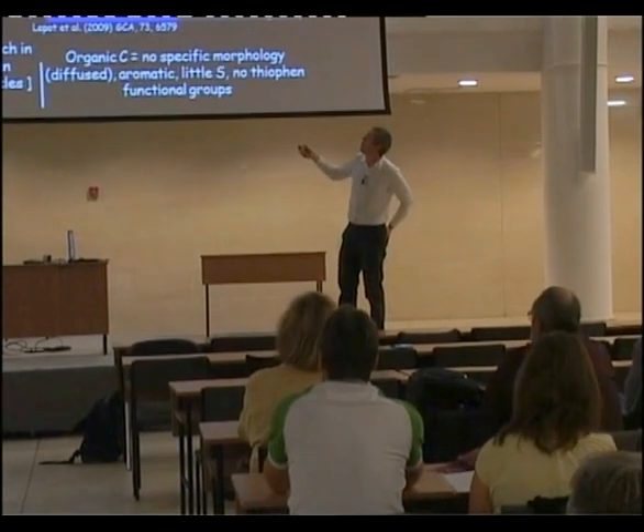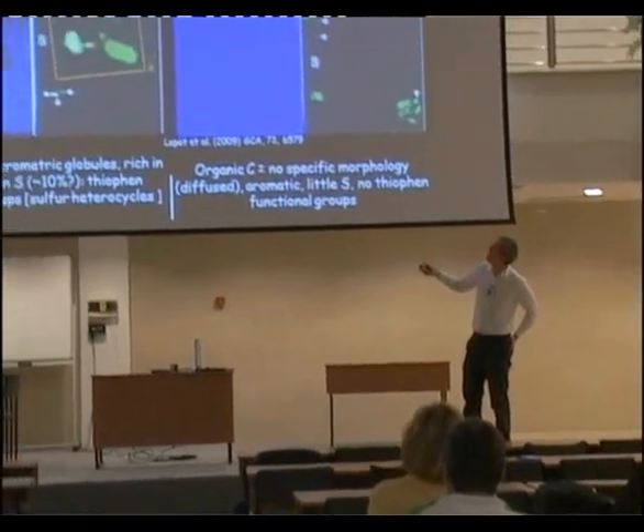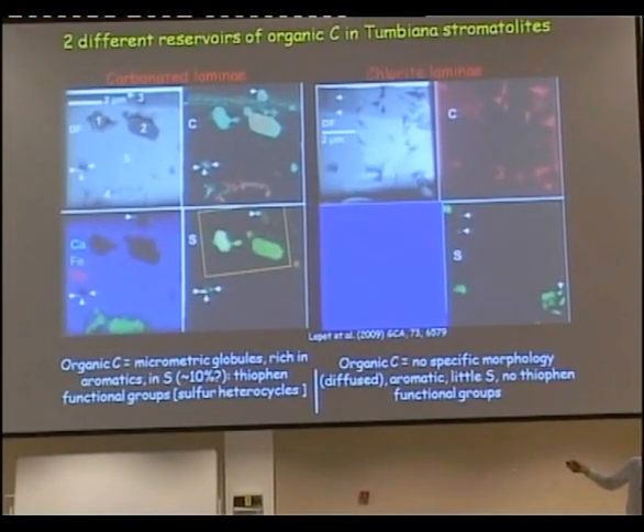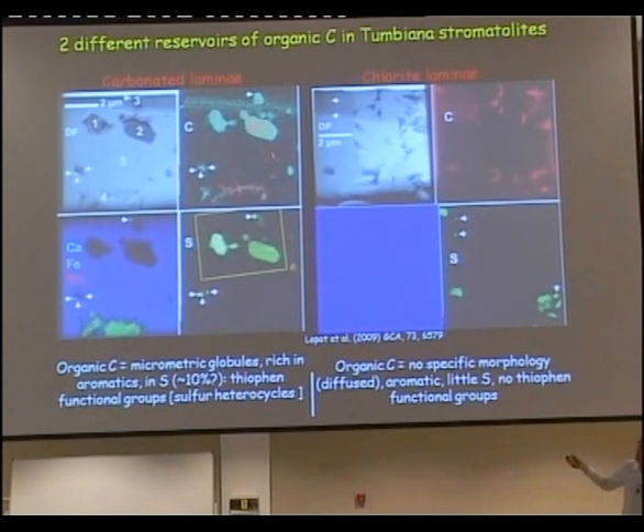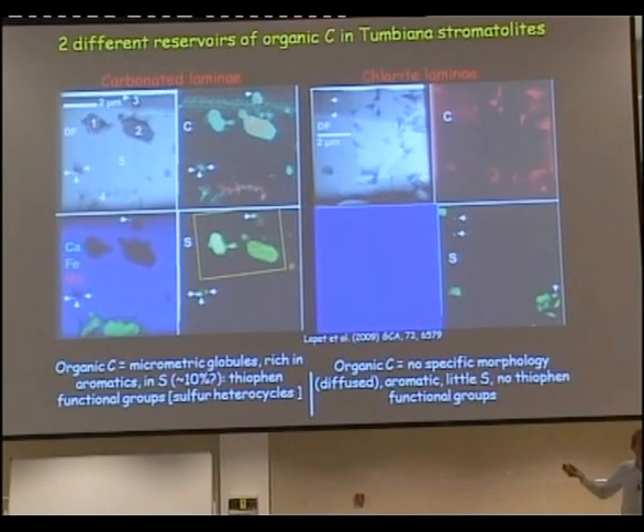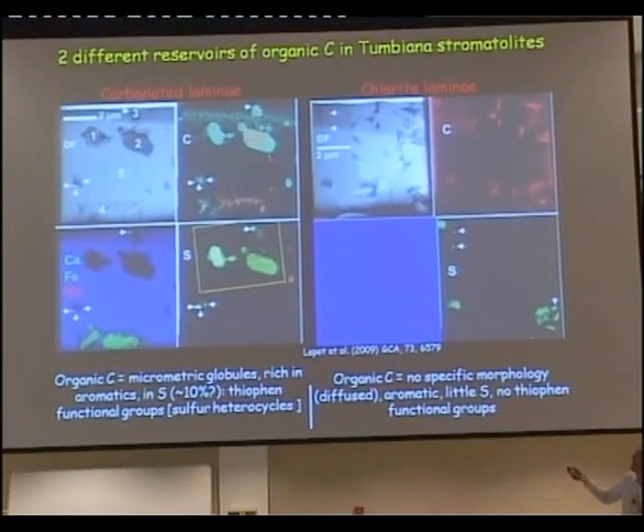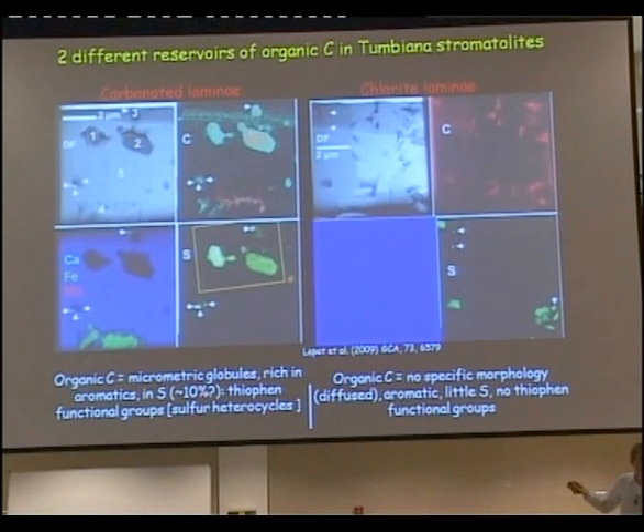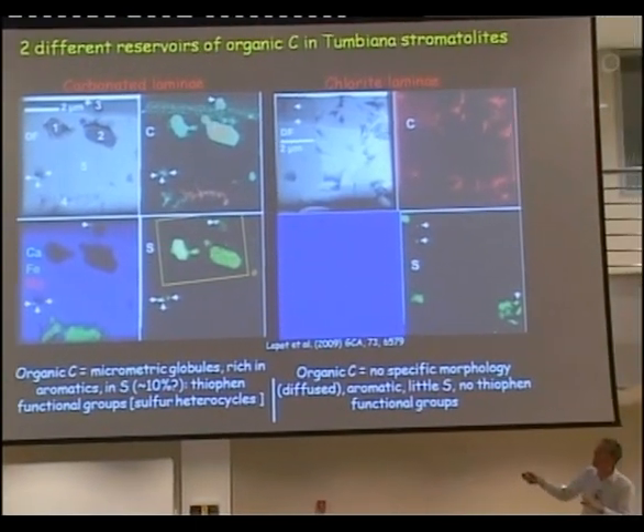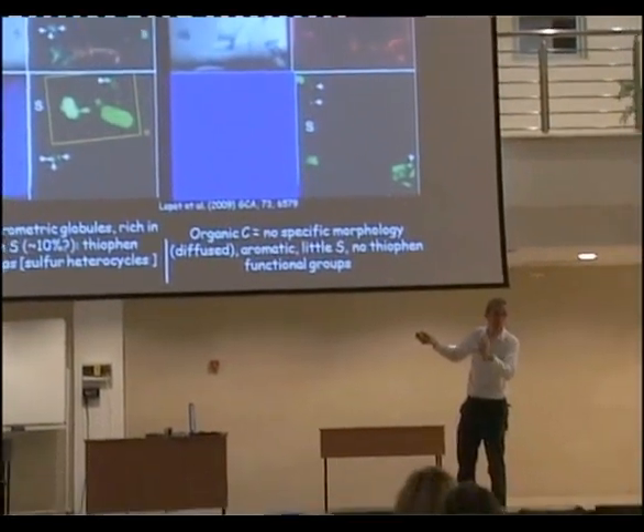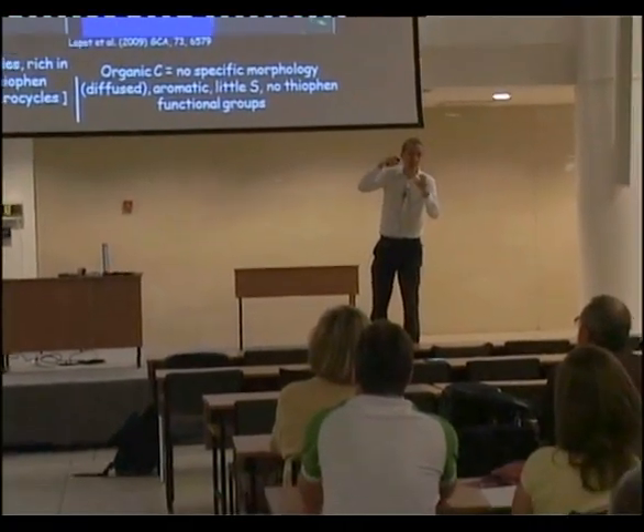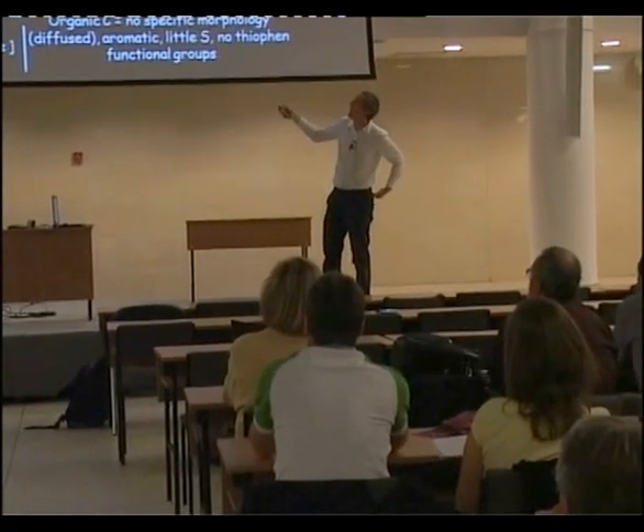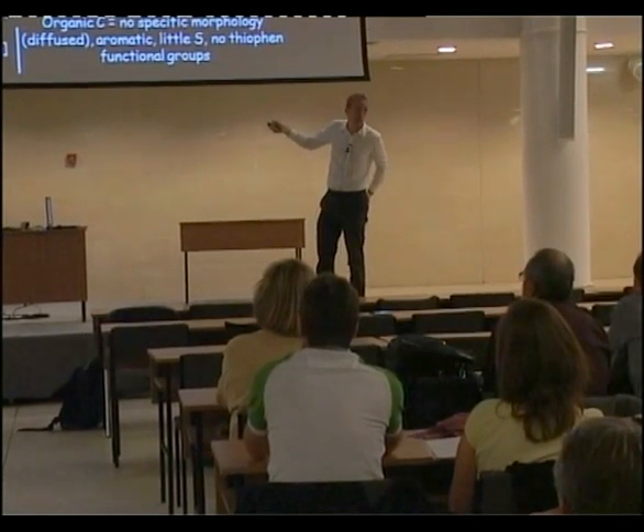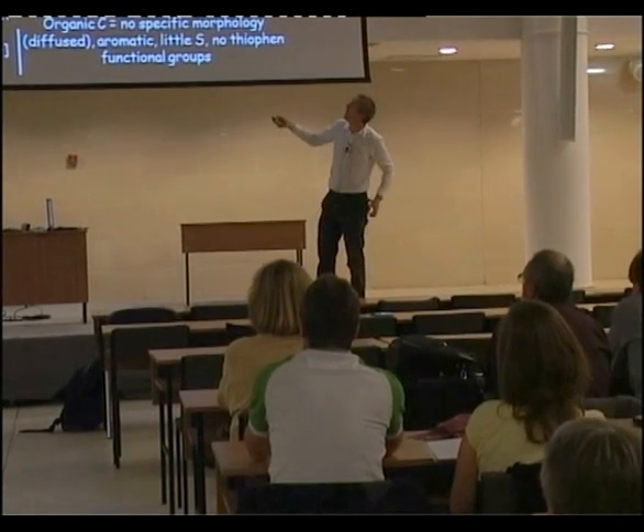So the way we explain it is that at the time you form the carbonates, there was some organic carbon here plus sulfides. This sulfide interact with the organic carbon. There was no iron at the time we formed this laminate. There was no iron, so the sulfides interact with organic carbon and so preserved the globule morphology of the organics.